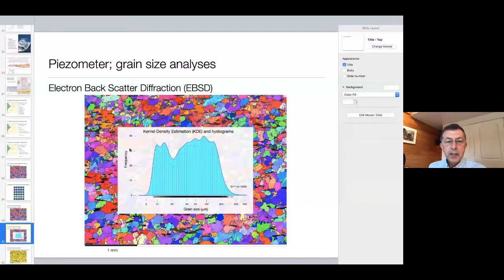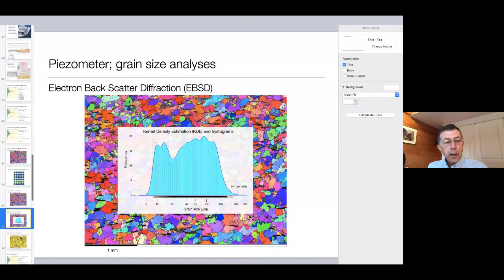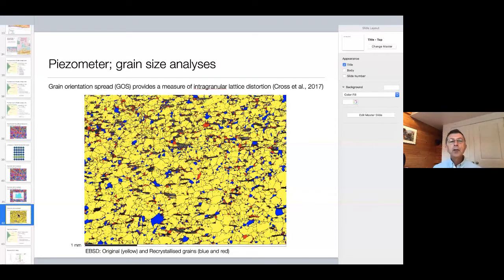This is a normalized frequency on the KDE diagram. And we see that there's a bimodal distribution of grain sizes. There are larger grains with a broad spectrum of sizes, and there are smaller grains, which are smaller than 20 microns on average, somewhere around 12, 15 microns. This is one way to do it, but an even better way is to actually map out the original grains, which are in yellow, and the recrystallized grains, which are in blue. This is done by measuring the density of lattice distortion, which is again obtained by the EBSD imaging.